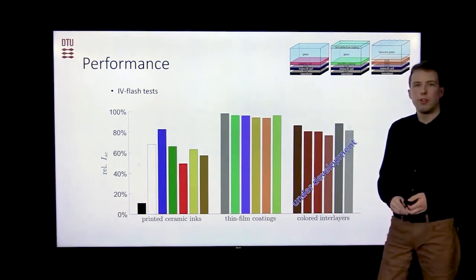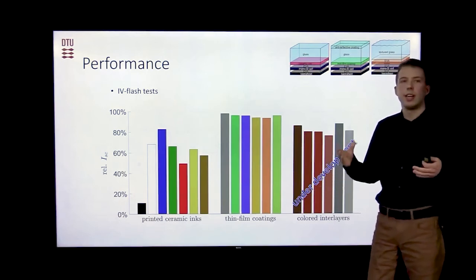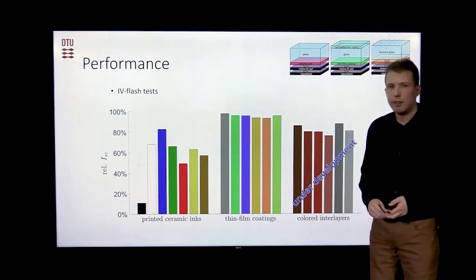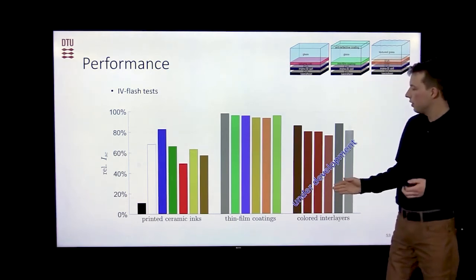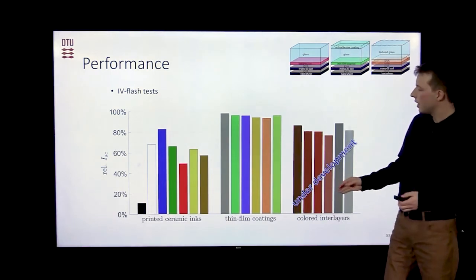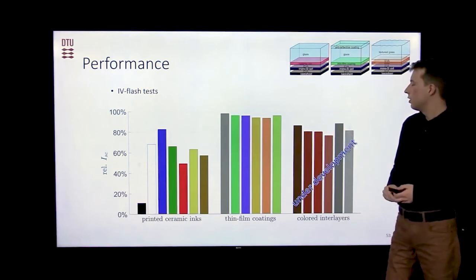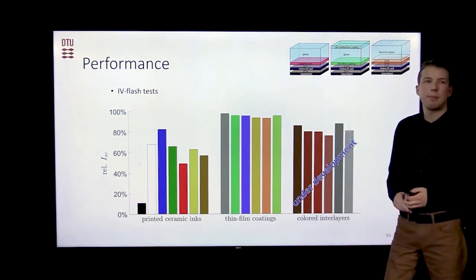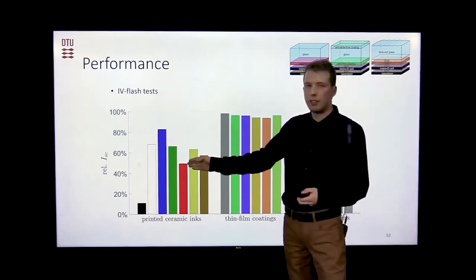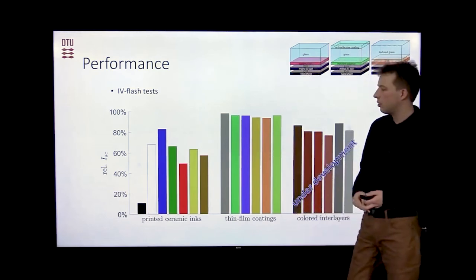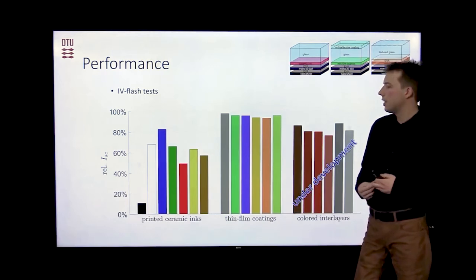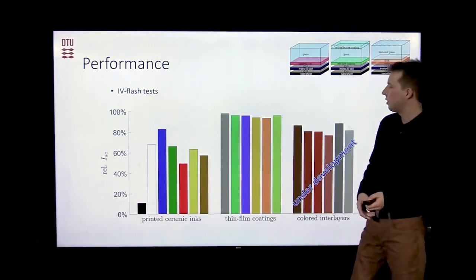However, as I mentioned before, that comes with the trade-off of having a very iridescent behavior and highly diverse angular appearance. Finally, if we look at the samples from Solenergie, I have to mention these are samples under development, so they might be improved, but still we can see a performance of about 80%. So we currently have about 20% loss. However, this is already very good, since if we compare it to red colored samples, this is the most difficult color to achieve in commercial applications, since the red color is the one which is most significant for PV production.